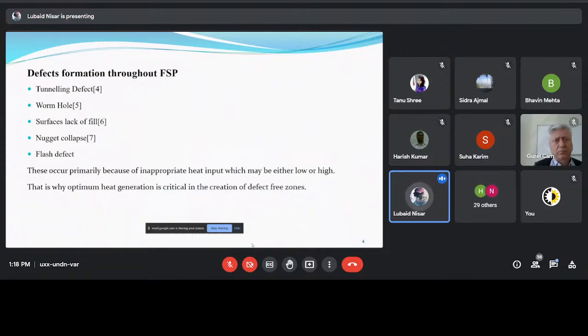The other one is the flash defect. This occurs due to high rotation speed, which produces a large amount of heat generation. When a large amount of heat is generated, the material becomes overly soft, and with the addition of shoulder pressure, the material is discharged from the edge of the processed zone in the form of flash. As we saw, these defects occur primarily because of the heat input. That is why optimum heat generation is critical in the creation of defect-free zones.